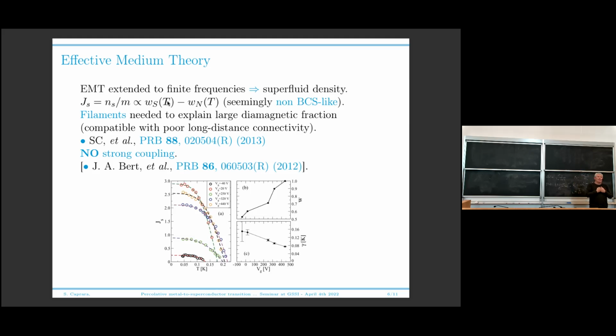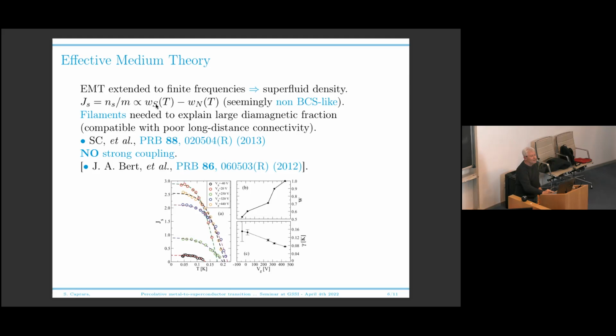And the nice thing about effective medium theory, where disorder is completely random, is that this is nothing but the difference between the fraction of superconducting clusters and the fraction of metallic clusters as a function of temperature, whenever this is greater than zero, which means that you need superconductivity to percolate in order to have a purely reactive response, which is, I would say, reasonable. Okay, this is with effective medium theory.